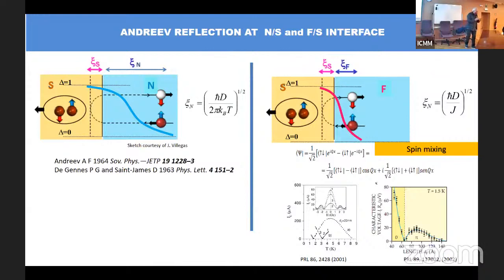The Josephson effect in principle is a two-terminal device, and you measure across the interface. So you need the high transparency, right? And we were not sure in principle whether we had it or not. It turns out that the transparency, I cannot tell you a number, but I can show you that this is very high.